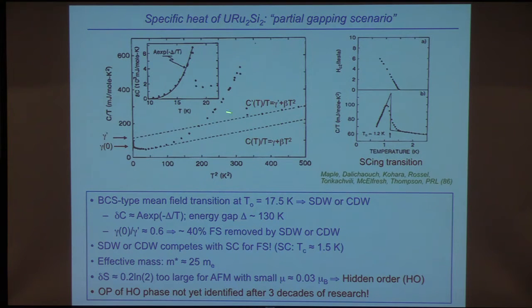Hidden order. And then, of course, the actual gamma before it becomes superconducting is this value right here. So if you take this ratio, then this suggests that about 40% of the Fermi surface is removed by what we thought was a spin or charge density wave. Okay? And then at lower temperatures, the rest of the Fermi surface is removed by the superconductivity.